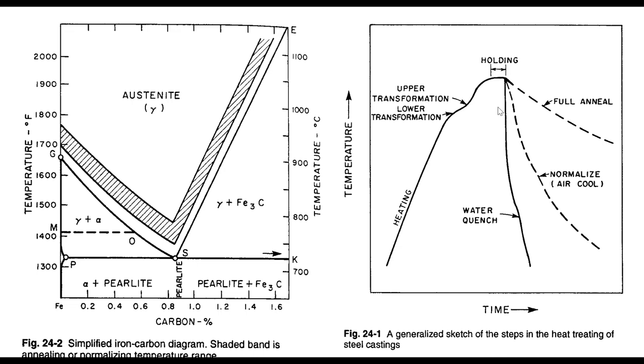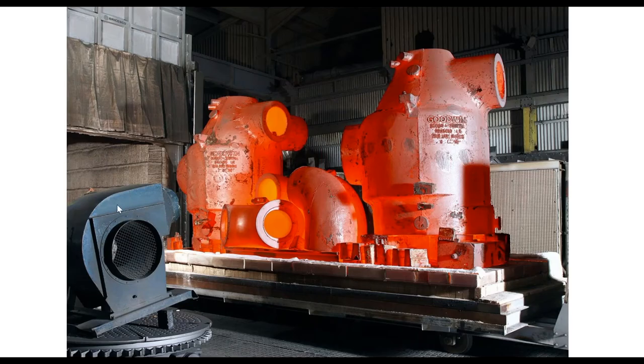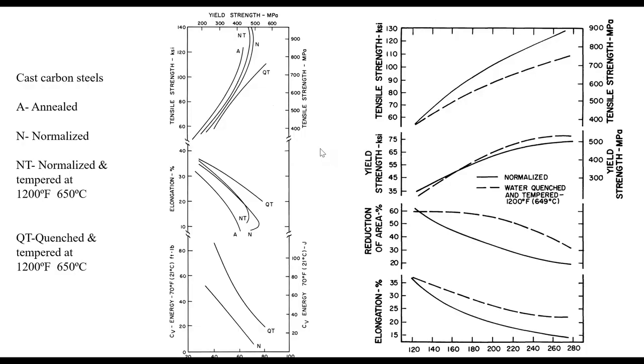When I water quench it, the carbon and the iron can't rearrange themselves to make these carbides, and because of that, I lock in the carbon. I get something that's really hard and really brittle, and so I have to temper it to make it softer. Annealing, I furnace cool. Normalizing, this is a fan, I air cool it.